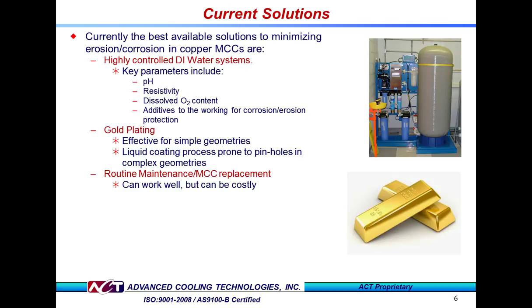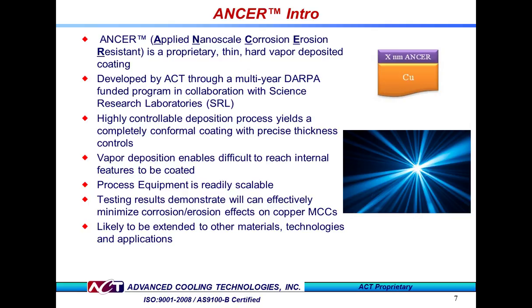The tightly controlled water systems are costly to implement and maintain, and, as we have seen, can actually contribute to corrosion erosion effects. Gold plating can provide good protection, but the liquid coating process is incapable of providing a pinhole-free, truly conformal coating for the complex, high aspect ratio internal features of these microchannel coolers. The presence of pinholes can result in some of the erosion-corrosion effects that we are trying to eliminate. Routine maintenance replacement of the microchannel coolers is expensive, not only in terms of cost, but also in loss of productivity from extra downtime. So it is a problem currently without a good solution.